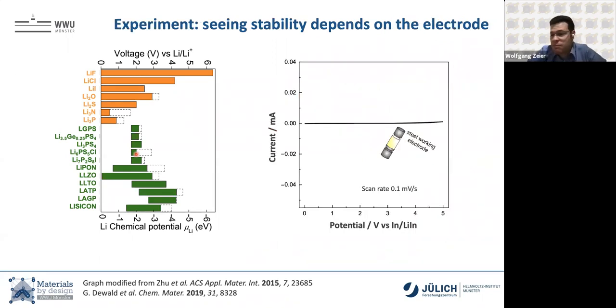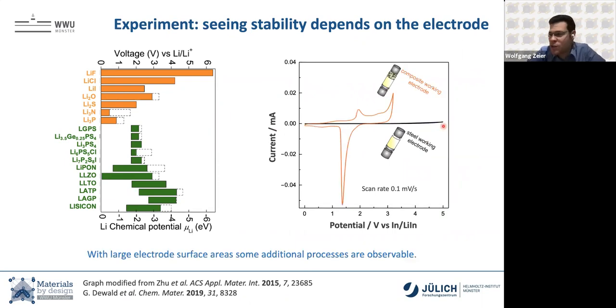And interestingly enough, if you run a typical CV of a solid electrolyte with planar electrodes, like most people do, these materials are stable up to 5 volts. Well, if you use an electrode that has larger surface areas, or you make a composite out of it, you already see in your CV that there's a lot happening. So they're not that stable.